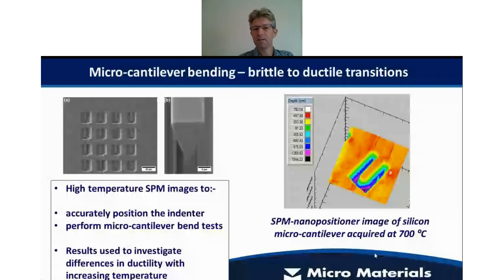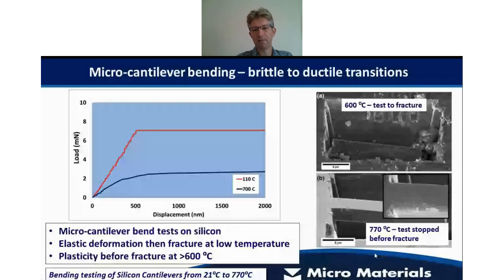Another type of thing you can do is pillar testing, but also you can do micro cantilever bend testing. This is some work, again, from Oxford University. Here we have a focused ion beam milled array of micro cantilevers, and we image over the top of one of those cantilevers using essentially the tip as the stylus in an SPM experiment. We can then use that image to very precisely target where we want to do our bending test. That's very important, because it goes into the maths to determine things such as the yield stress and modulus with temperature. We can also look at differences in ductility with increasing temperature. So we get very nice images. That's effectively a high temperature SPM image, if you like, with the integrated nanopositioner, taken at 700 degrees on a micro cantilever machined in a silicon surface.